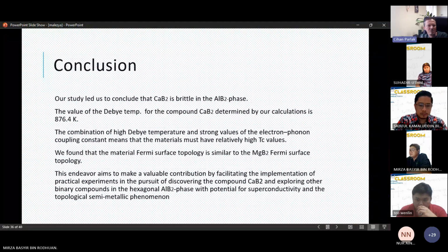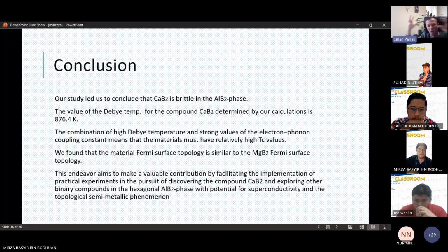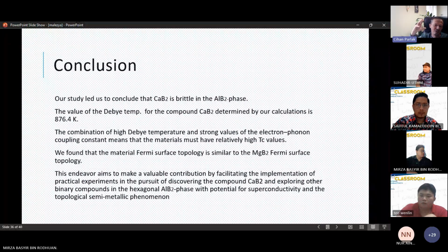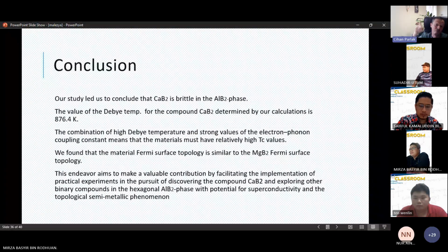876.4 Kelvin. This means, and the electron-phonon coupling constants, calcium diboride will have a relatively high TC if we can synthesize this. And the electronic band structure and the Fermi surfaces show us its electronic structure. It is not much different from the MgB2 structure. The difference between the TC values probably will be caused by higher phonon frequencies for MgB2. Next slide, please.